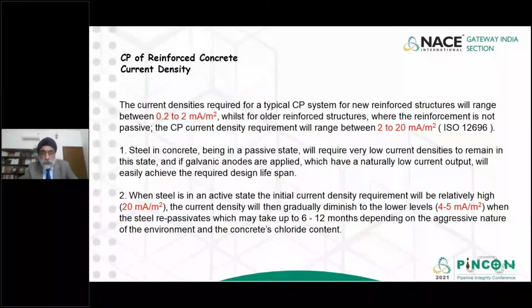Now, the current densities which we normally design vary from 0.2 to 2 milliampere per meter square. Where the reinforcement is not passive, and we suspect that the chloride ions will continue to impregnate through the concrete into the rebar, then we design based on much higher current densities, which could range from 2 to 20 milliampere per meter square. So depending on the type of soil, the type of concrete we select, and the type of rebar we are using, the current densities could range anything from 0.2 to 20 milliampere per meter square. So selecting the right current density is very important in ensuring that these reinforced concrete structures, if protected by ICCP, remain in a passive state for the entire design life.